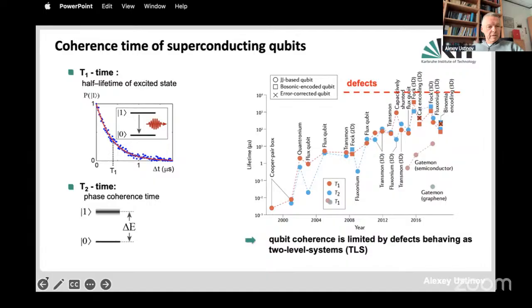Now, the environment also acts back on these devices by applying random fields, which you cannot control. And these random fields lead to the fluctuation of the energy level separation, which primarily leads to the dephasing. So this means that by controlling this device with specific frequency, you will get some uncontrolled dephasing, change of the phase of the quantum state, which can be formed between those two states if you, for example, make a superposition of those.